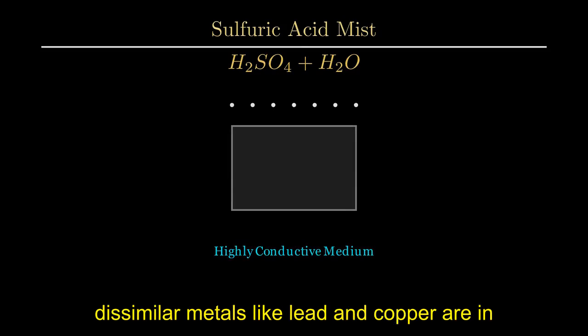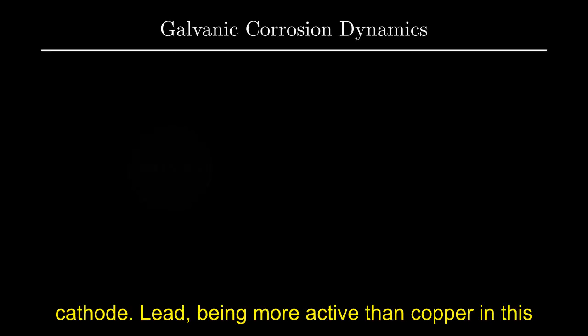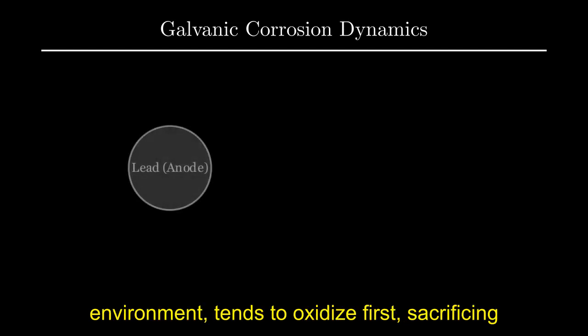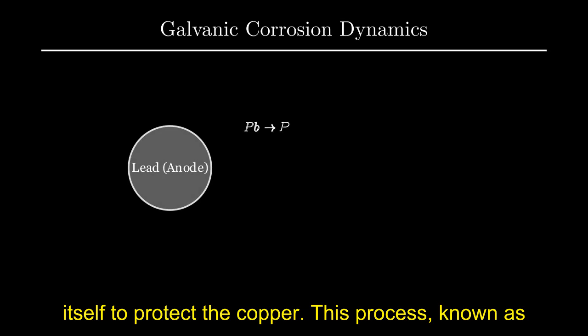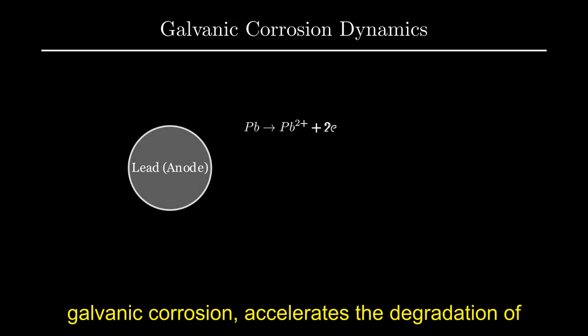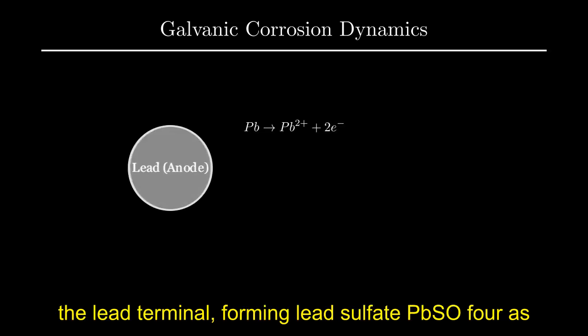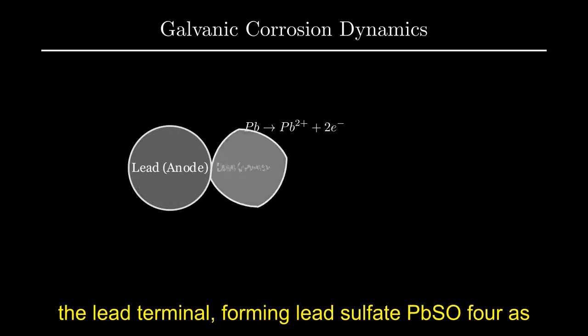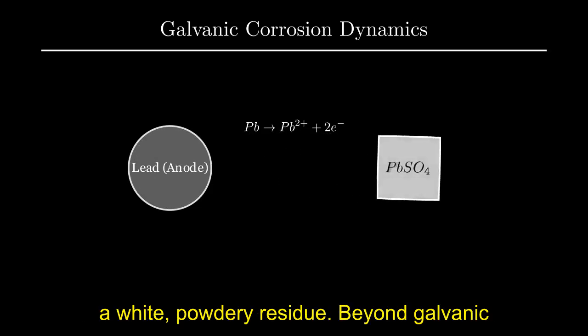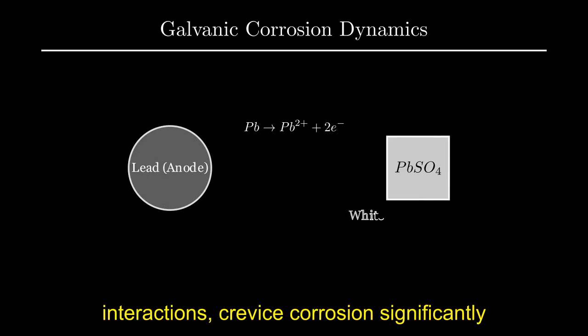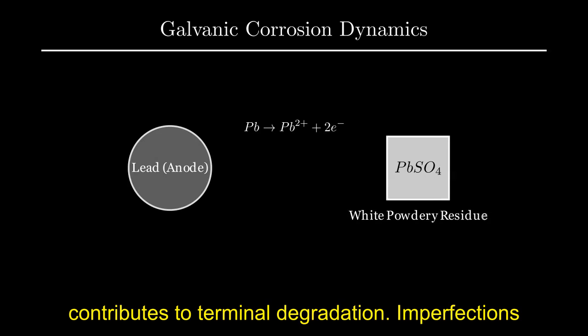When dissimilar metals like lead and copper are in electrical contact and exposed to an electrolyte, one metal acts as an anode and the other as a cathode. Lead, being more active than copper in this environment, tends to oxidize first, sacrificing itself to protect the copper. This process, known as galvanic corrosion, accelerates the degradation of the lead terminal, forming lead sulfate, PbSO4, as a white, powdery residue. Beyond galvanic interactions, crevice corrosion significantly contributes to terminal degradation.